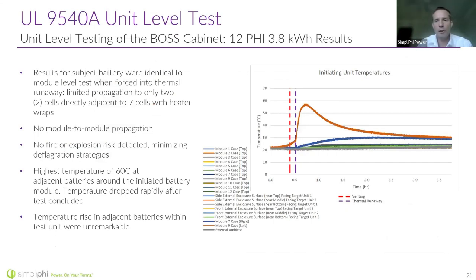Okay, so what we're doing here is we're going to force this battery cell into thermal runaway. We're going to look at the temperature that results, and we're going to look at the venting that occurs. Once you get the cell temperatures hot enough, you're going to have venting. That venting can then produce thermal runaway, and we're going to see if it's mitigated, see if it stops on its own. Some important things to note here.